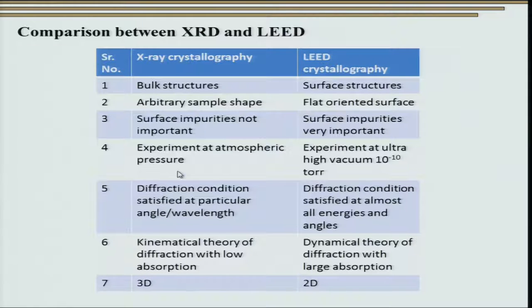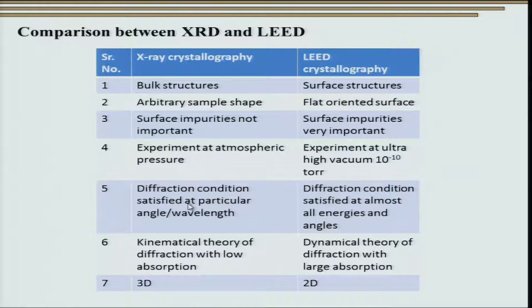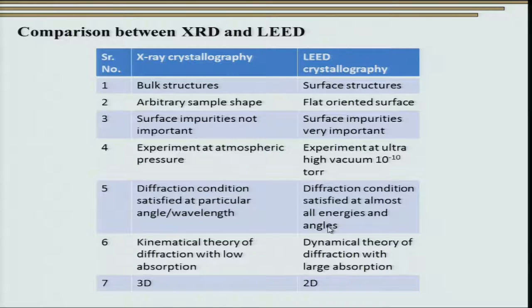X-ray diffraction experiments are generally carried out at ambient temperatures and conditions. However, we need ultra-high vacuum for carrying out LEED crystallography. For x-ray crystallography, the diffraction condition is satisfied for a particular wavelength or angle depending on Bragg's diffraction condition. However, the diffraction conditions are pretty much relaxed and get satisfied at almost all energies and angles when it comes to low energy electron diffraction.